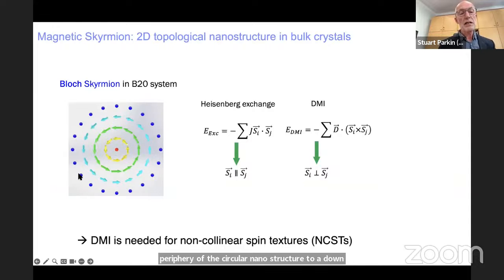You can see now the magnetization is rotating so that the moments are perpendicular to the radius, parallel to the domain wall, in contrast to the Neel type domain wall, which I just introduced in the previous foil. This is a very interesting object, which is found in systems with strong unidirectional anisotropy, typically in tetragonal or hexagonal systems, low symmetry systems. And this DMI vector gives rise to lowering the energy when you form these boundaries with this chiral structure.